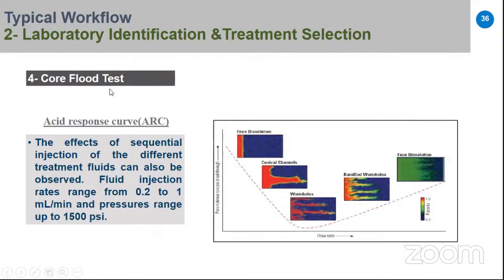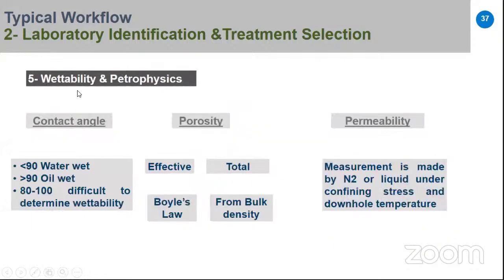We can also make a core flood test to determine, as we said before, the optimum injection rate. Also, we need to know the wettability of the reservoir and the petrophysics like porosity and permeability. Usually, wettability is from contact angle. If the contact angle is less than 90, we have a water wet reservoir. If the contact angle is greater than 90, we have an oil wet reservoir. Also, from the core analysis, we have effective porosity and total porosity, and from core analysis we can also get permeability.